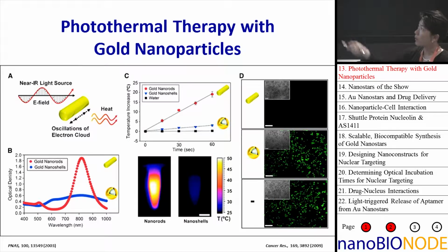So what they're doing is they're comparing gold nanorods. These are on the order of, say, 10 to 20 nanometers in diameter. They can be 30 to 50 nanometers long. Catherine Murphy here at UIUC is an expert in gold nanorods. And so if you look at the extinction spectrum, you can see that they both overlap at long wavelengths. And for the same gold content, which they determined using inductively coupled plasma mass spectrometry, you can see that the absorption and scattering cross-section of the gold nanorod was slightly larger.